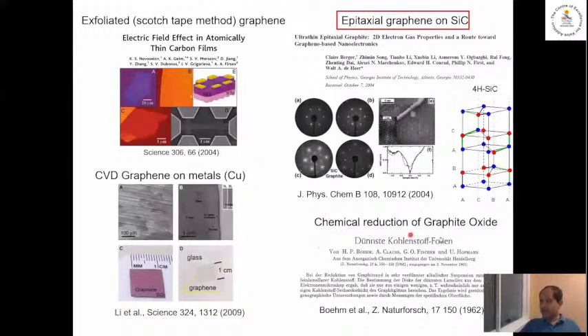And then graphene could also be realized by chemically reducing graphite oxide. This was discussed in the 60s. And then the fourth method, which we used, is epitaxial graphene on silicon carbide. So the idea is silicon carbide has silicon and carbon in it in this crystalline arrangement. You take silicon carbide, put it in an oven, heat it to a very high temperature, and what happens is that the silicon comes off, and the carbon stays back and then rearranges into a graphene film on the surface. So you get graphene on silicon carbide, and this is called epitaxial graphene.